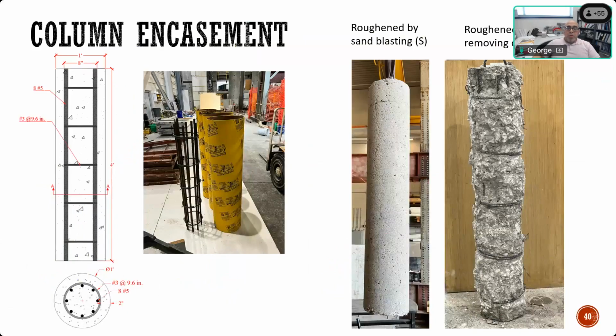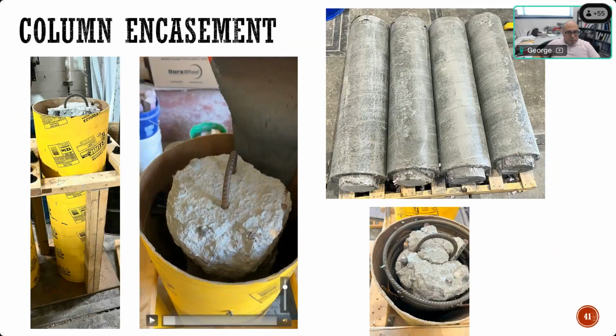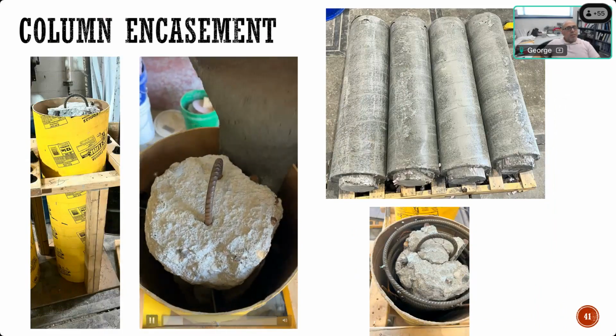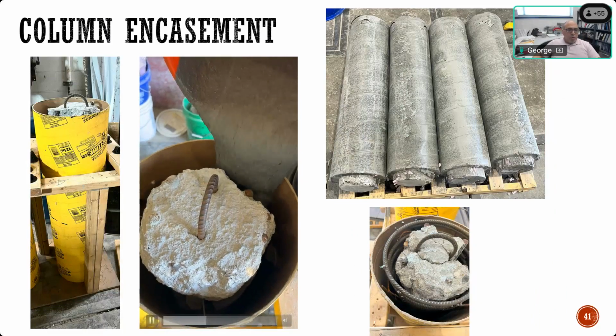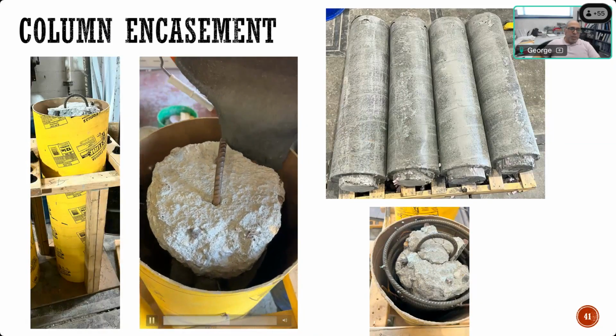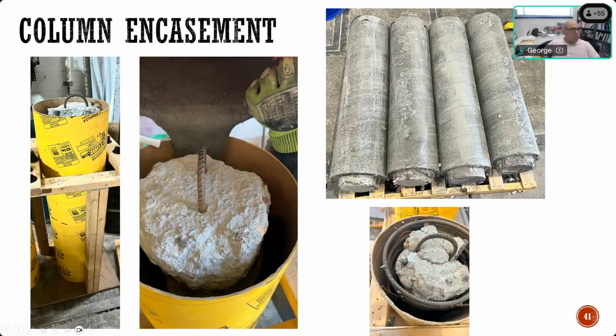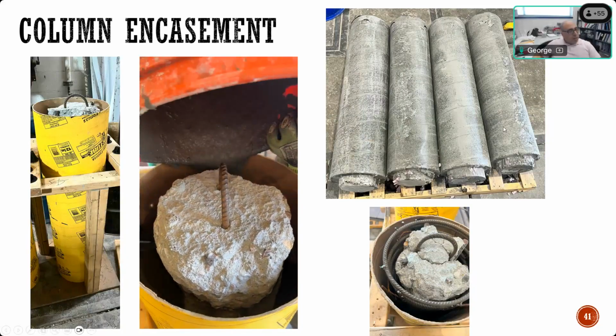We looked at how you can encase existing columns using UHPC. So we built a few specimens, and some of them were sandblasted, others were after removing the covers and then formed around those and added 2 inches of UHPC all around the column. So this is how we form around the column, adding UHPC. That's how it looks in the picture here after adding 2 inches all around.